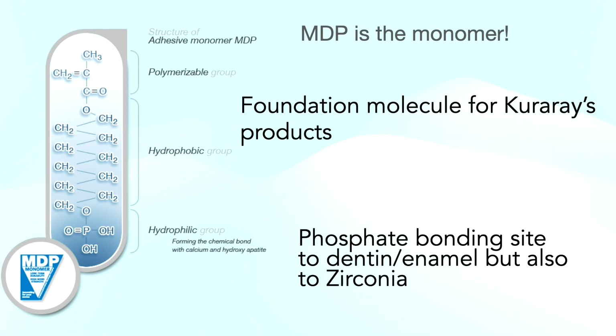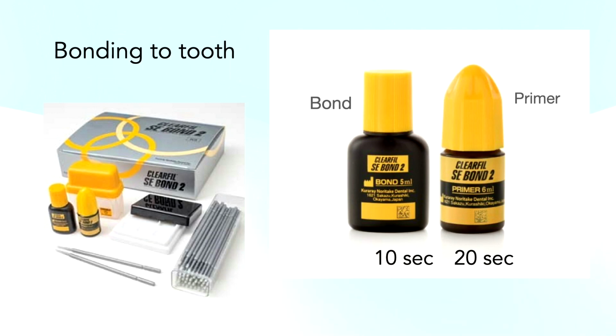Here's MDP. So we have a phosphate monomer, or moiety down here, and a vinyl moiety up here. So this is the hydrophilic end that bonds to tooth structure, but it also bonds to zirconia. And then you have the hydrophobic end, and that's bonding to your composite. Okay. And this is a semi-hands-on course without the hands-on, so it's eyes-on. So here's SE2. The simple rule with almost all self-etching systems is the 20-second, 10-second rule. 20 seconds with the primer, 10 seconds with the bond, and light cure, okay?